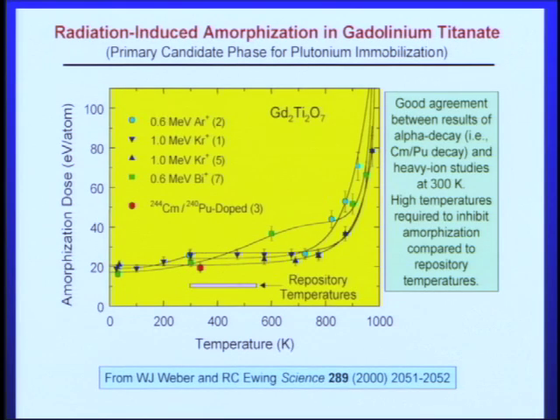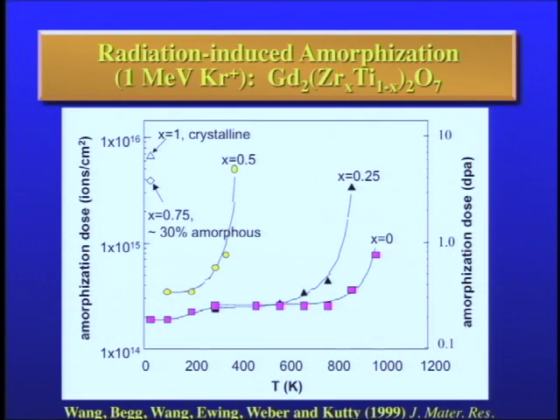Okay. And then you can see there were all types of experiments done using ion beam techniques, but the most important was to demonstrate that the curium-doped and plutonium-doped samples gave us the same dose for amorphization at room temperature as the ion beam experiments.